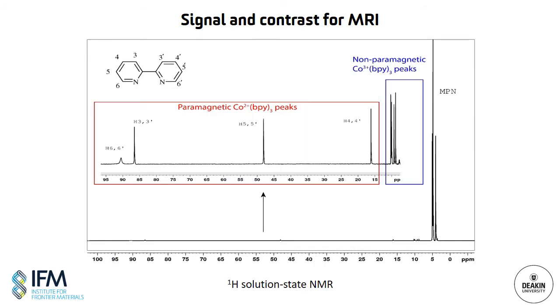So protons are the obvious choice for MRI, although I will note here that we're also using fluorine-19 imaging, but I'm not going to show any of those results today. So this is what the proton NMR spectrum looks like from this electrolyte. You can see that the spectrum is dominated by the signal from the MPN solvent, and we can also see smaller peaks here from the cobalt ligands, clustered around 10 ppm for the non-paramagnetic form, and then spread out over much larger shift ranges for the paramagnetic cobalt 2+.